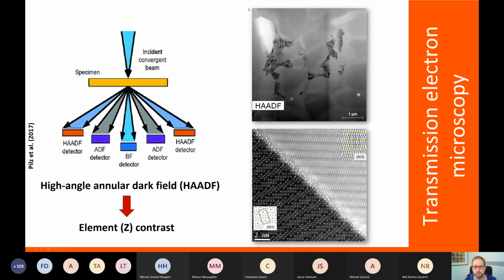So here on the top right-hand image, you see a quite high resolution image with probably a field of view of about 5 micrometers. The contrast here scales with atomic numbers. So we know already we have 3 different phases. We have this very bright phase here, which could be an iron oxide. We could do an X-ray analysis at a later point in a fairly homogeneous matrix. And then we have this intermediate phase here, which in this case is actually clay. So we have a technique inside a TEM similar to an SEM, where we can look at element contrast images. And we can actually do this at very high resolutions.